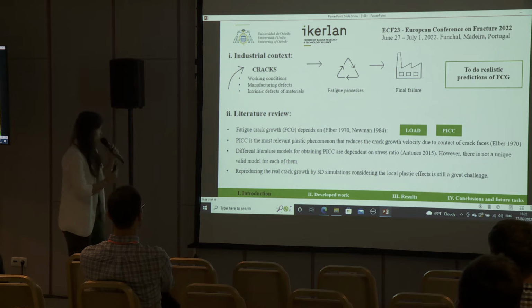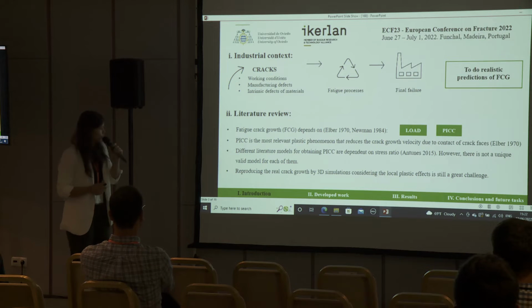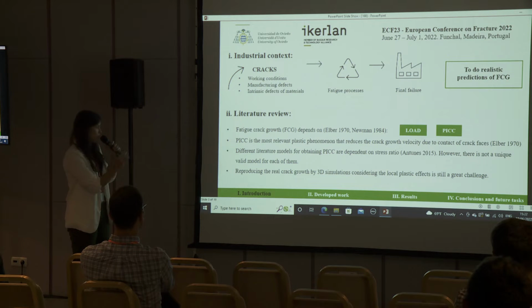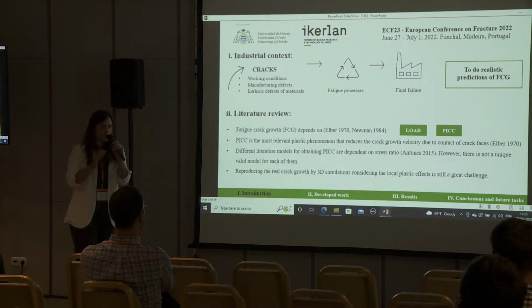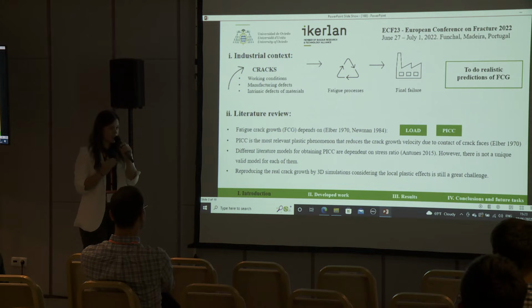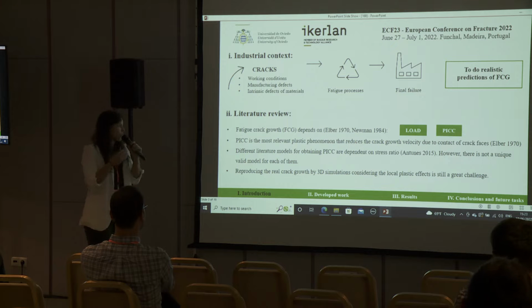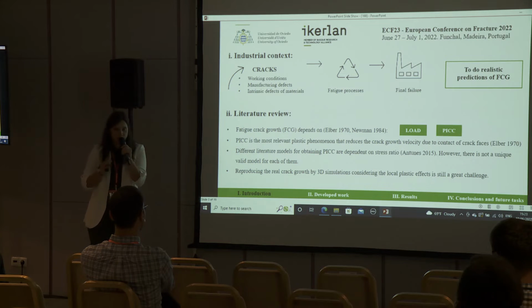The most relevant conclusions derived from the literature review are, first, the fatigue crack growth depends on the loads and the plasticity-induced crack closure, or PIC. This PIC is the most relevant plastic phenomenon that reduces the crack growth velocity due to the contact between the crack faces. Moreover, different literature models for obtaining this PIC are dependent on the stress ratio. However, there is not a unique valid model for each of them. And finally, despite the improvement of numerical techniques, reproducing the real crack growth by 3D simulations is still a great challenge.